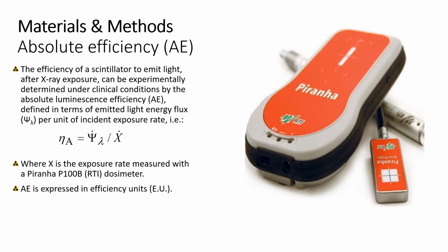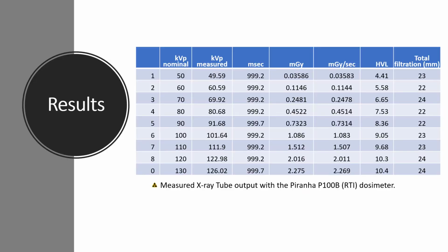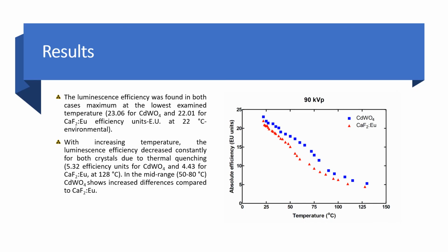The efficiency of a scintillator to emit light after X-ray exposure can be experimentally determined under clinical conditions by the absolute luminescence efficiency, defined in terms of emitted light energy flux per unit of incident exposure rate. This table shows the measured X-ray tube output with the Piranha dosimeter used in our experiments. The luminescence efficiency was found in both cases to be maximum at the lowest examined temperature, which was 23.06 efficiency units for cadmium tungstate and 22.01 efficiency units for calcium fluoride doped with europium.